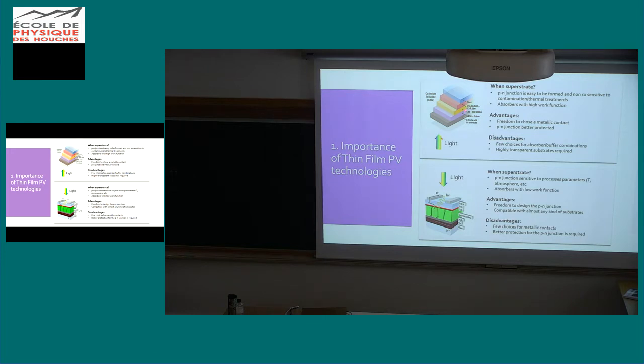In the superstrate, remember, we first fabricate the N-type semiconductor and then the P-type absorber. And normally for the P-type absorber, you need at least 500 degrees. So this requires that the N-type semiconductor withstand 500 degrees at least. The disadvantage is that, once again, you have few combinations of buffer and absorber, and you need, of course, a highly transparent substrate because you are illuminating from the substrate. So it's not compatible with an opaque substrate.